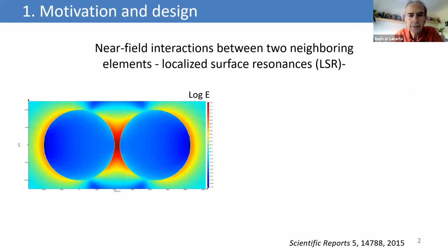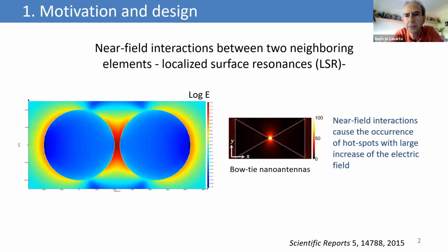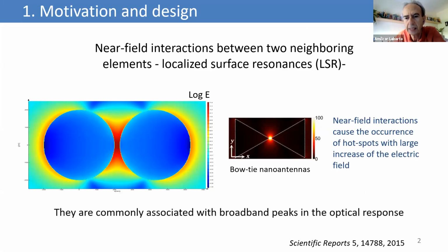So you know that when we have two elements in close proximity, there is a strong interaction between them, and then we have near-field interactions, and these near-field interactions produce hotspots, like in a bow tie nanoantenna. And this kind of excitation corresponds in general to low energies, so they are located in the near infrared, and they are associated with broadband peaks.